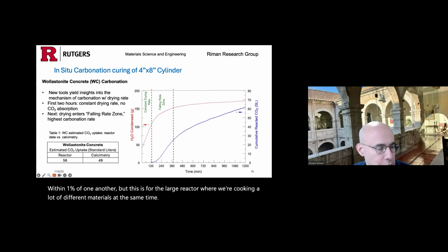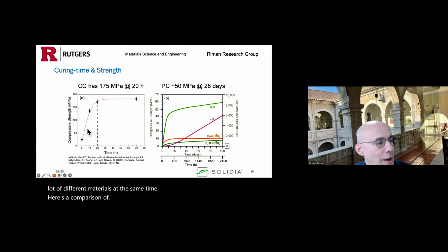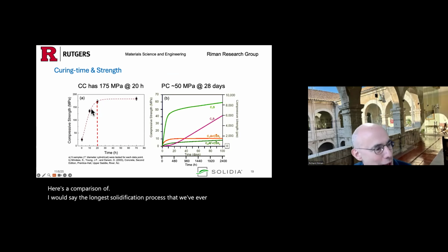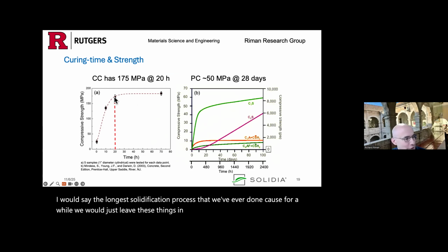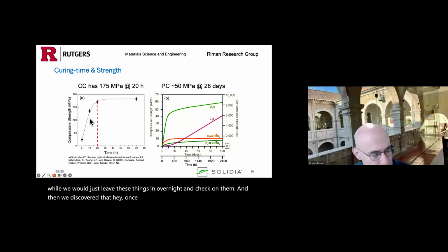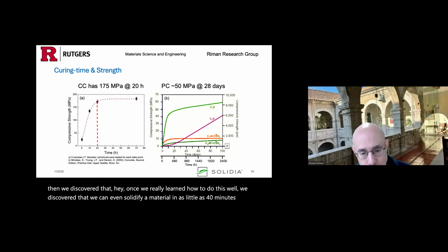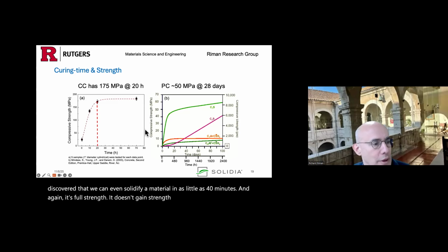Here's a comparison of, I would say, the longest solidification process that we've ever done, because for a while we would just leave these things in overnight and check on them. And then we discovered that, hey, once we really learned how to do this well, we can even solidify a material in as little as 40 minutes. And again, it's full strength. It doesn't gain strength later on like cement and concrete. So even in our lengthy process that I'm showing you here we're looking at time in days, and this is time in hours. So it's a much faster process.